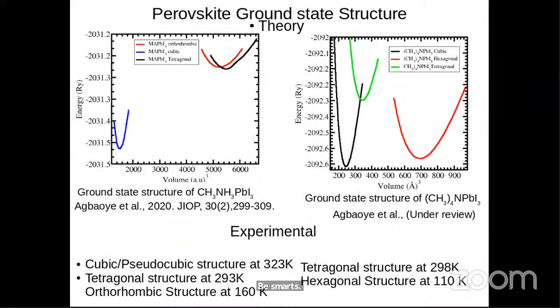Then the structure of perovskite, experimental studies have shown that for methyl ammonium lead iodide, we have three basic phases. The first one is the cubic or pseudocubic phase that exists at high temperature. The second one is the tetragonal structure that exists at medium temperature, and at low temperature, we have the orthorhombic structure. And as theorists, we would like to work with the ground state of this material.